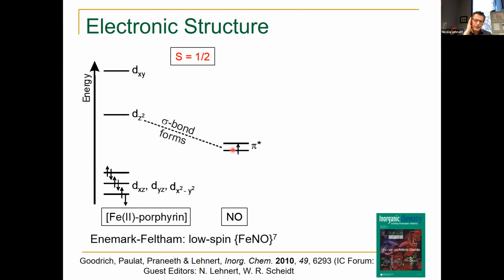I also want to quickly introduce the Enemark-Feltham notation here. Nitric oxide is what we call, in inorganic chemistry, a non-innocent ligand, which means it's redox active. And if you bind NO to a transition metal complex, you don't always know what the electronic structure is. So the Enemark-Feltham notation is an electron counting system where we just count the number of valence electrons of the iron NO unit. So we have 6 d electrons of iron, 1 pi star electron of NO. So we call this an FeNO7. And then the iron is in the low spin state. So we call this a low spin FeNO7.